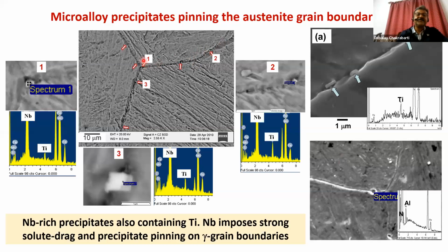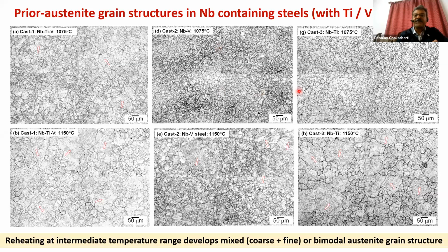And these precipitates control the austenite grain size, because before rolling, we have to reheat the steel to the austenite domain at 1200 or 1150. And at that temperature, these precipitates actually pin the grain boundaries. Here is the evidence of scanning electron micrographs showing the precipitates, white dots, pinning the austenite grain boundaries. As a result, what happens? At low temperature soaking, which we generally do not prefer in our rolling mill or section mill, you may find a more uniform austenite grain structure, but at high temperature, that can be a highly non-uniform grain structure.